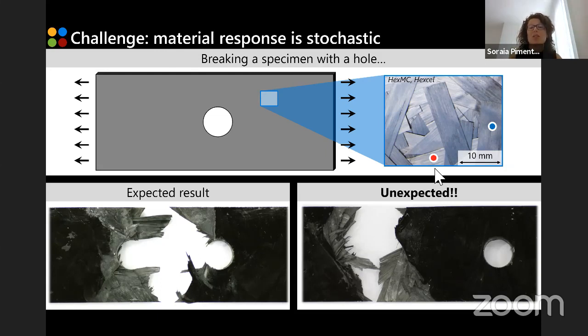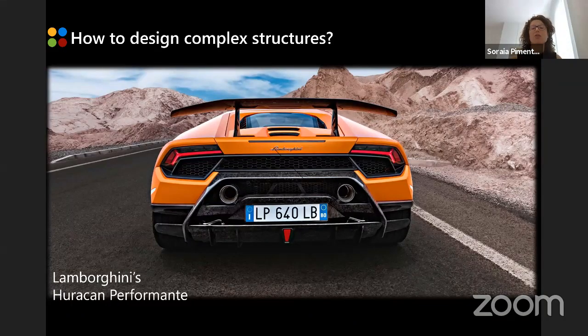But this basically happens because the properties of these materials are different from one point to another. That difference is in part controlled by flow, as I mentioned in the previous section, but it's also controlled by a stochastic process. So it's controlled by chance as well. So if you make two specimens nominally in an identical way, one of them will behave in a certain way, the other will behave in another, and there is no way for you to know what you get until you actually test the specimens. And this, of course, brings a question about how to use these materials in complex structures such as the one that you can see here. So if you want to use these materials in a car, how can you design the car so that it's still lightweight and makes full use of the properties of composites, but is safe within this material variability that we actually have?